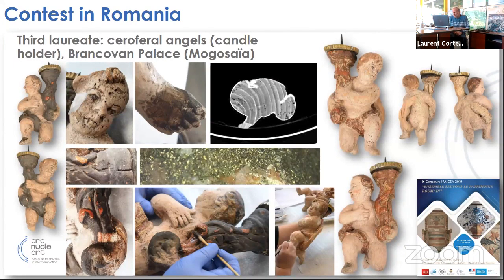The third laureate were two angels or putti that are also candle holders, also from the Mogosaïa. Here it was necessary to remove a bronzing layer. Bronzing is a metal paint layer intended to look like bronze or gold. In this case, it was completely oxidized and almost black, as you can see on the candle holder. So it was removed, and you can see after the restoration.